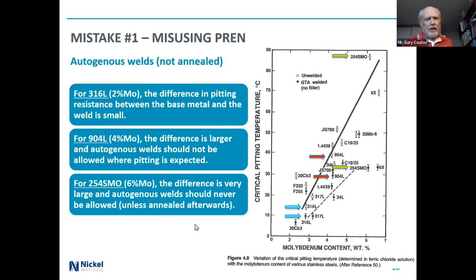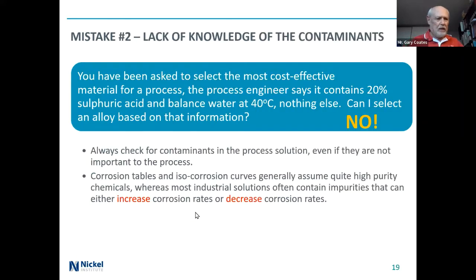And I just want to emphasize, these apply to autogenous welds only. If you have filler metal, it's a completely different picture, and with filler metal, the filler metals are compensated, so they give corrosion resistance very close to the base metal. Maybe not the same, but very close. Well, that's enough about PREN.